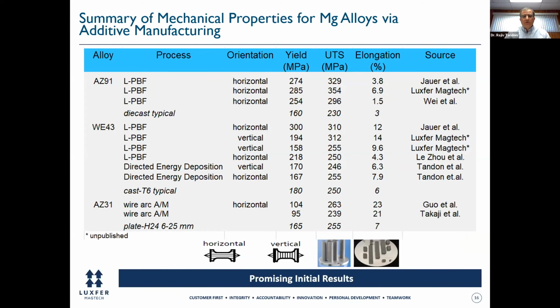So just to give you a sense for where the effort has led to, I have listed AZ91 and WE-43, and I've pulled this information from the public domain, including some of our own data, some of which is unpublished, but it goes on to show you the promising potential for magnesium. For example, in AZ91, you look at a typical die cast property of 160 in yield and 230 in UTS, and laser powder bed fusion processes have been able to clearly achieve significantly better results with respect to the yield and the UTS. And it doesn't take into account different groups working with different powders, different machine setups, and so forth. But the trend is clear that if you get your process parameters right, you are capturing the advantage of the very fine scale microstructure that you can obtain.